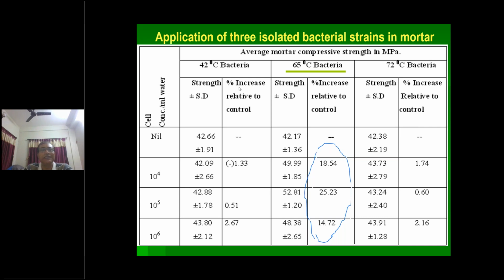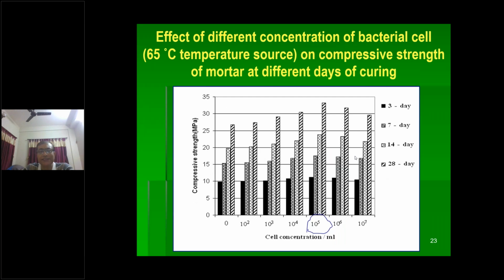If you have seen, with respect to without any cell concentrations at 3 days, at 42 degrees C and 72 degrees C, there is not so much improvement. But with the 65 degrees C temperature, we have got a lot of improvement. In fact, at 10 to the power 5, we are getting 25% improvement in strength. This is the same as shown in the bar chart diagrams.